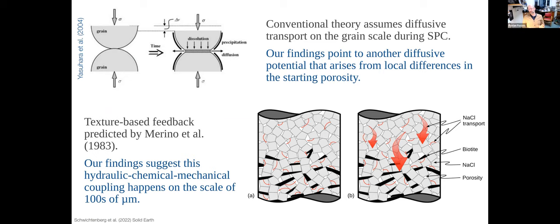Imagine that sample that I showed you. The porosity will not be perfectly homogeneously distributed across that sample. It does fluctuate slightly, and it fluctuates slightly more where the biotite is, right? Biotite, different morphology, slightly different surface chemistry, or massively different surface chemistry, in fact. So there's a different porosity at the onset of the experiment in the biotite bearing layer than there is in the salt layer.